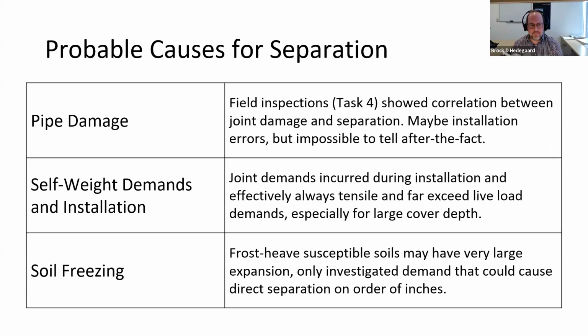degradation of these pipes. In terms of the self-weight demands and installation, this far exceeds your live load demands in general, especially for large cover depths. So that also can lend credence to why we see higher cover pipes being more at risk for joint separation, because the weight of that embankment is separating the whole system, and there's just more built up tension in that type of system. So there's more likelihood that you'll have a separation. And then again, soil freezing is going to be our most likely cause for direct separation at the ends.